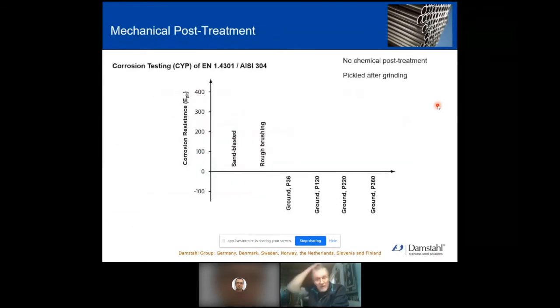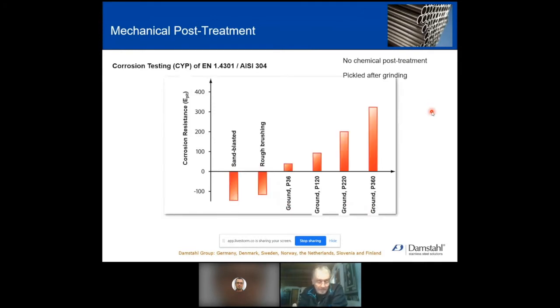And this we can actually measure, which we did at the university quite a few years ago, where we tested through a method called cyclic polarization various sheets made of 4301, the 304 class, and we measured the pitting potential in a dilute chloride solution. We tested six different surface treatments: sand-blasted, a rough brushing, and then polished to grit 36, which is very rough, and down to 360. The corrosion resistance was a bit like this. And it's very easy to see that the finer the surface, the better the corrosion resistance.